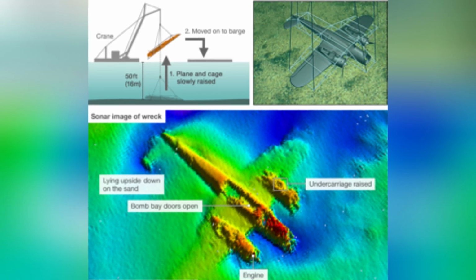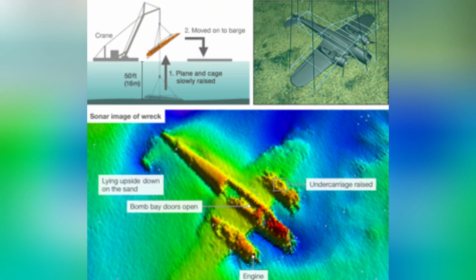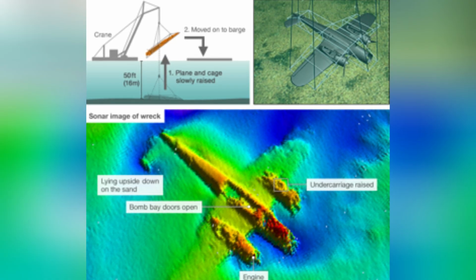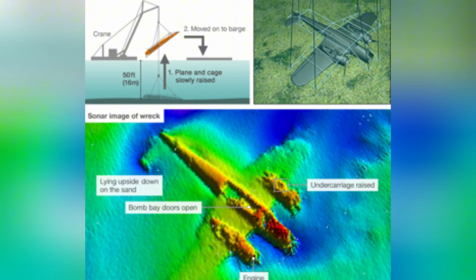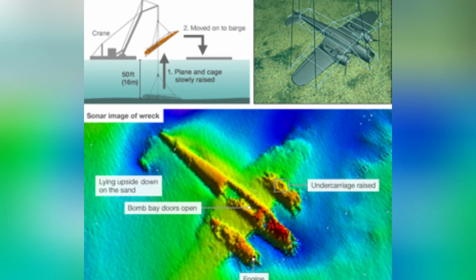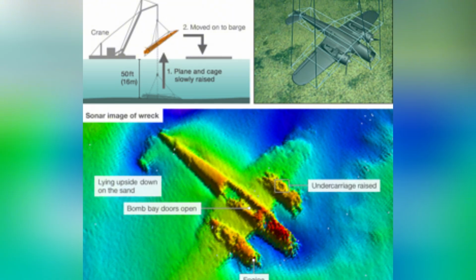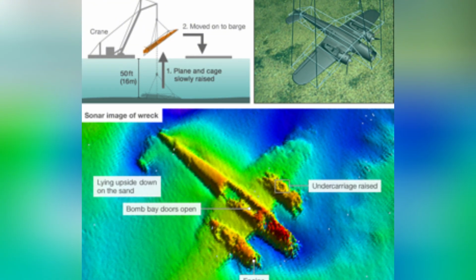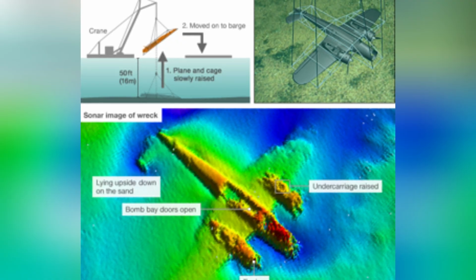The structural integrity of key members was increasingly uncertain as corrosion progressed and as the sands alternately buried and exposed the airframe. The engineering assessment was absolute. If the aircraft remained on the Goodwin Sands, the combination of tidal current stress and chemical dissolution would reduce the airframe to a debris field of unrecognizable fragments within a few years. The objective was clear, but the physical constraints were severe. The goal was to recover the airframe intact for stabilization and forensic analysis.